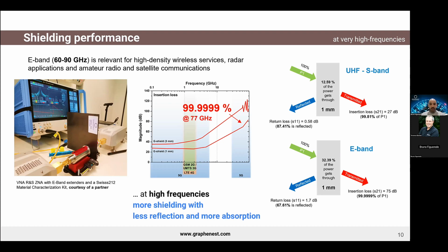But now let's take a look at the plot in the middle, where I'm plotting the insertion loss as a function of the frequency again. So decibels as a function of gigahertz. And as you can see in the plot, the performance of the graphene-based PVC is exponentially enhanced, attaining an attenuation of 99.9999% at 77 gigahertz. But why such a big difference? So let's make the exercise on the right.